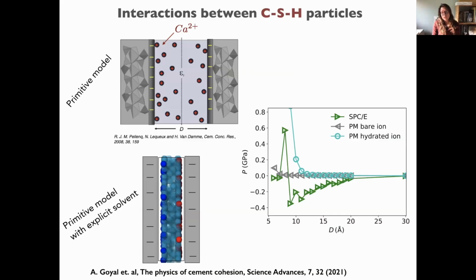For example, if we look at the gray curve, which is basically the bare ion, we see that we have a repulsive interaction. If we increase the size of the ion because it has a hydration shell, we will see that this repulsion is pushed a bit further.